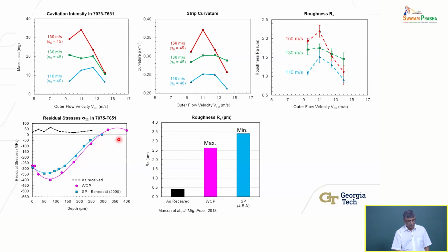This also shows you the residual stress distribution, these elastic stresses in the material measured through X-ray diffraction. And you can see here residual stress. You can see it's very deep, it's compressive. This pink colored curve shows you it's deeper. This is data from literature using shot peening, okay?